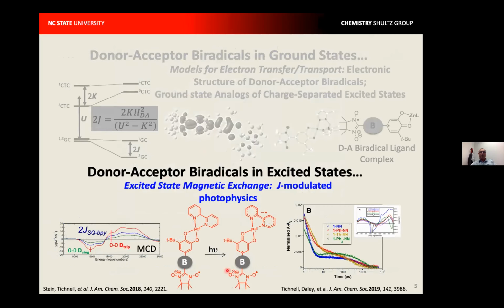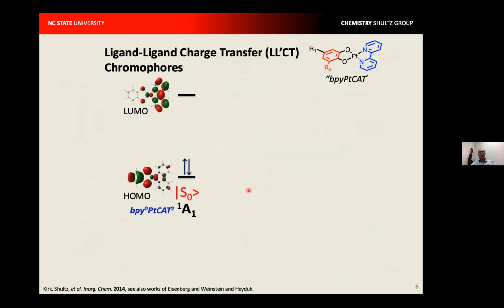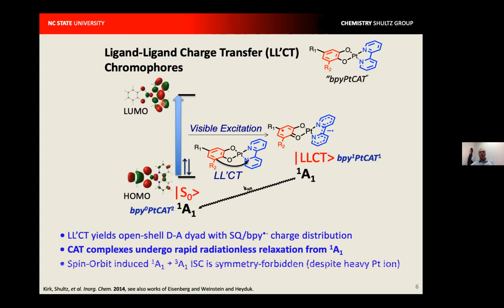So these molecules that we use to photochemically generate donor acceptor biradicals in excited states, we're interested in demonstrating manifestations of magnetic exchange in photoinduced excited states. And these chromophores are great platforms for this type of project. And so, as I mentioned, there's a ligand-to-ligand charge transfer in these chromophores. And in fact, computationally, you can observe that the highest occupied molecular orbital is about 90% catecholate donor with a little bit of metal and diimine character, while the LUMO is predominantly a diimine with a little bit of metal and catecholate character. And so that ligand-to-ligand charge transfer results in a near unit electron transfer from the catecholate over to the bipyridine and makes these ligand biradical excited states.